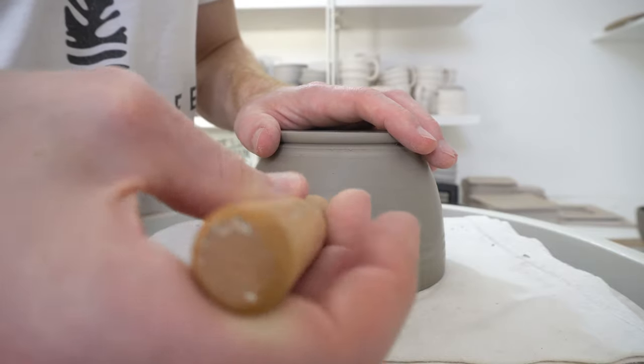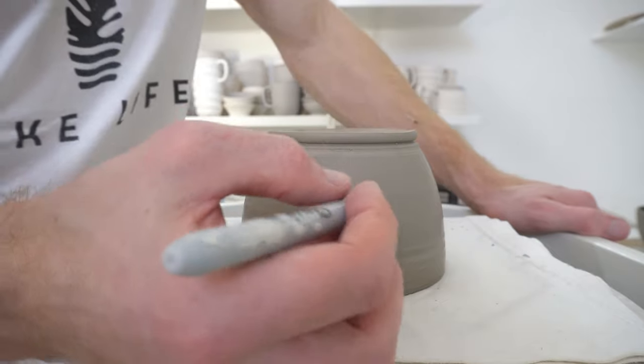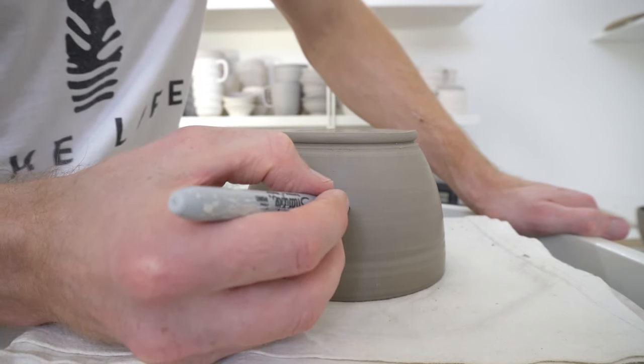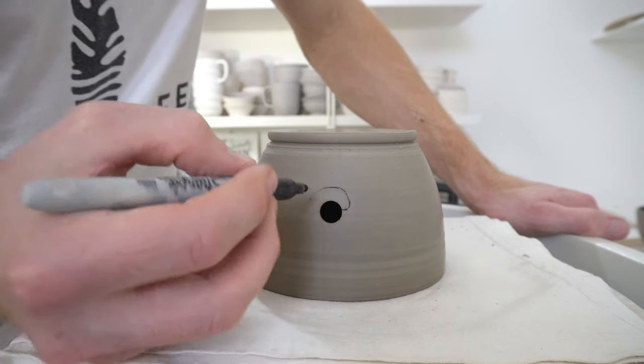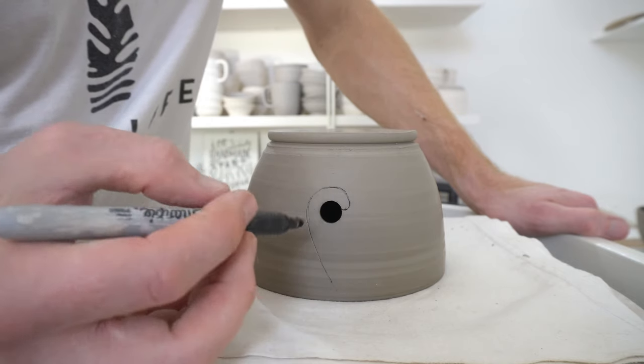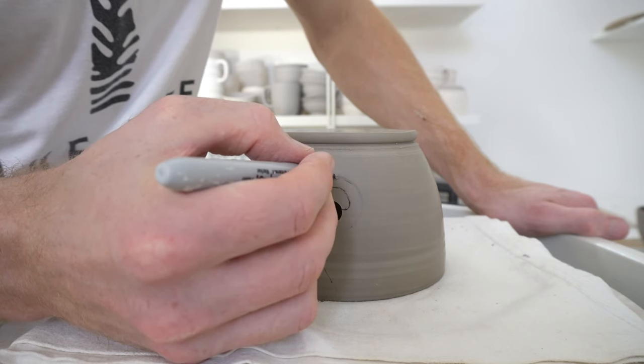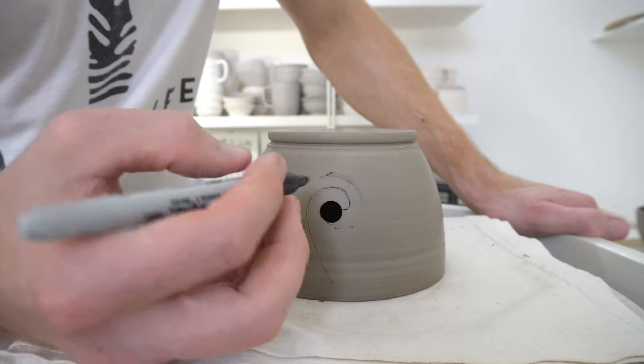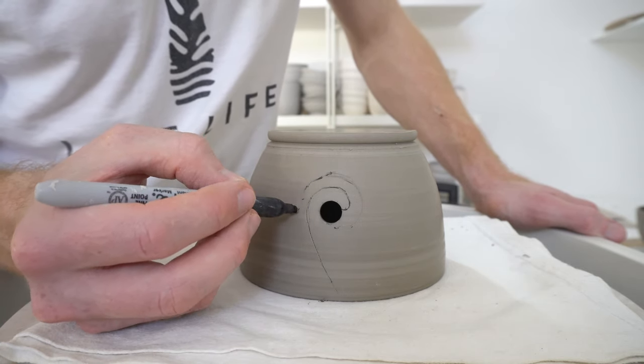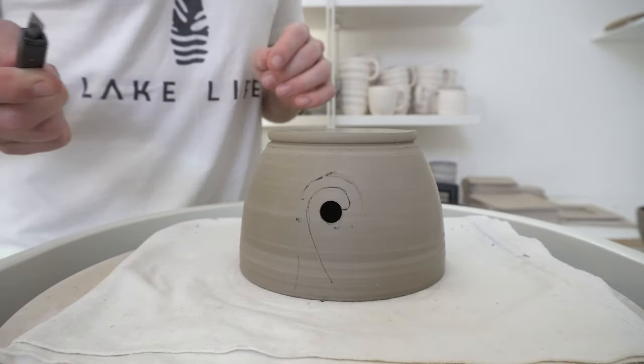Make the starting hole and then you can draw on greenware with a Sharpie and it'll burn off completely in the bisque. So what I want to do is come out of that hole about halfway up and then loop round underneath, trying to stay a similar distance away from the hole, and then up, and then the other line comes off around the top. You don't want this to be too narrow because any drip of glaze coming off that will close it if they're just a few millimetres apart. So it's worth erring on the side of too wide rather than too narrow.